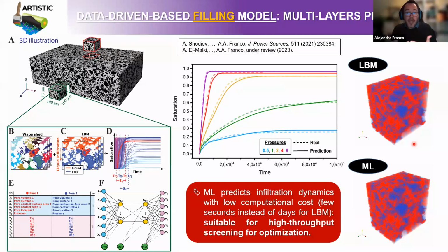And this paves the way towards the high throughput screening of the influence of electrolyte properties and electrode microstructures on the speed and the easiness of this infiltration process of the electrodes by the electrolyte, right? And this is actually a paper that we initially published in 2021, describing this method. And now we have a paper under review where we are demonstrating the use of this method for high throughput screening of electrolyte chemistries and also electrode microstructures in the facility to infiltrate the electrodes by the liquid electrolyte. Hopefully this paper will come out soon.